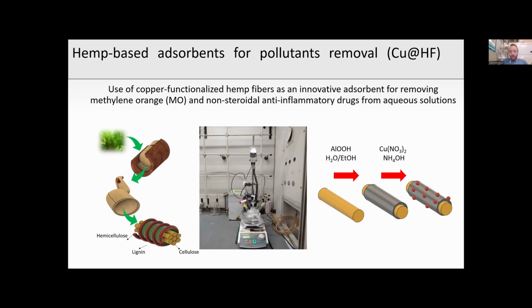So here I would like to introduce you to several approaches to modify the surface of this material in order to improve its adsorption properties. The first approach concerned the use of a double-step process to modify the surface of hemp fiber through a first precipitation of aluminum hydroxide in order to activate and modify the surface of hemp fibers, followed by the co-precipitation of copper oxide nanoparticles on the surface of hemp fiber in order to design a novel kind of adsorbent for removing several classes of contaminants.